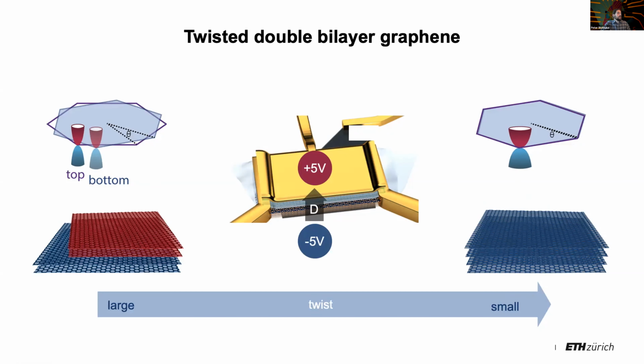And now the outer layers, they're attached to a boron nitride, right? Whereas the inner layers see two graphene layers in their close proximity. So their electrostatic environment is slightly different, and that leads to a charge transfer from the outer to the inner layers. And now you see you have, even without applying anything, you will open up a band gap by this small electric field that pops up.